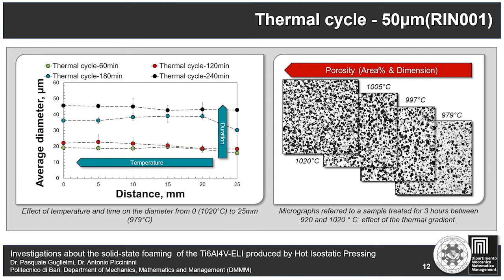The same consideration is also valid in the case of a thermal cycle. In fact, an increase in terms of porosity is visible according to the duration of the process. In this case, contrary to the isothermal case, a low effect is due to the temperature gradient recorded in the longitudinal direction of the sample, as also shown by the micrographs on the right. Moving from right to left, the temperature and the porosity increase, but the porosity level for the 20 millimeters in the center of the sample can be considered almost constant.